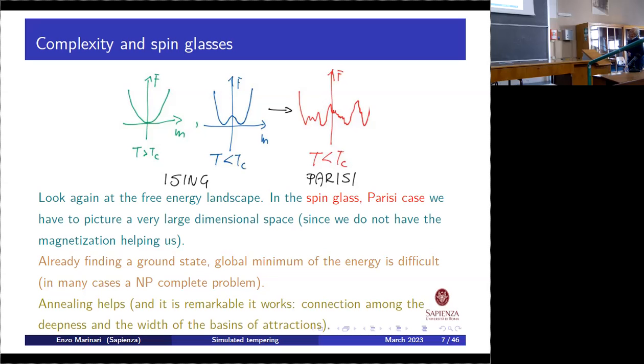So in this case, we have infinite barriers in the infinite volume limit that separate states that don't have an easy and direct symmetric relation with the other states. So we cannot use our little trick of the Ising model, where we do one state and we are done with everything. Here, we have to do it all, okay? And so this is the problem. If we want to study a system with multiple states by Monte Carlo, I need a Monte Carlo method that would allow me, during the dynamics, to pass these barriers that are indeed very high, infinite, in the infinite volume limit.